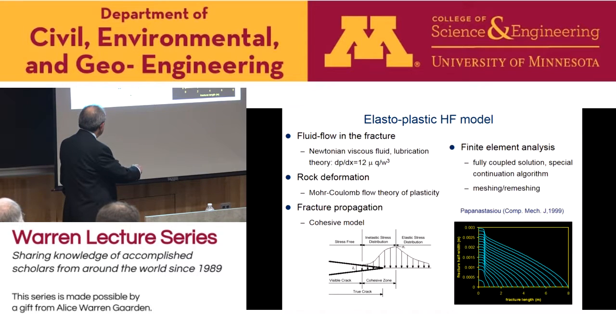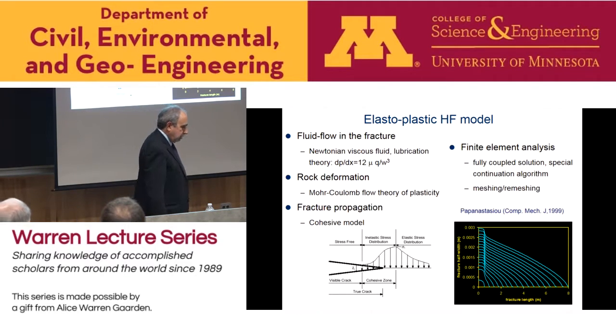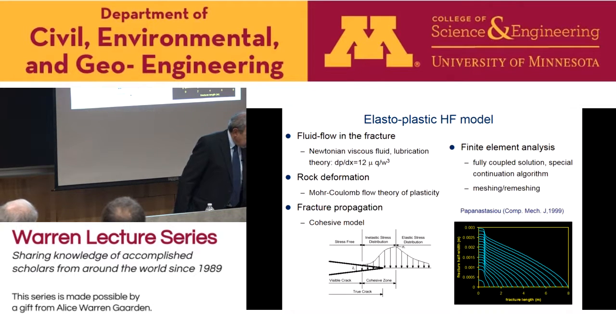Basically, this cohesive model expresses the stress carried in the area perpendicular to propagation as a function of the separation. As the stress increases near the fracture tip, it cannot go higher than the tensile strength of the rock, and then we follow a softening behavior until complete separation. Around this process zone, which we try to model through this cohesive model, there is a lot of detailed work done also by Joseph Labuz in this department, in the past and more recently.